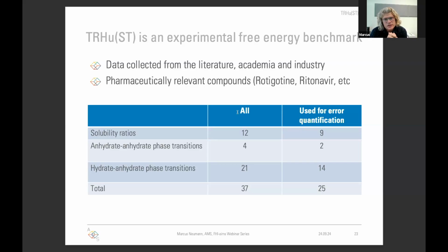Now you may wonder, why is there so little data? Well, the reason is that a lot of conditions need to be fulfilled. The crystal structures of all experimental forms must have been solved. There should not be massive disorder, because otherwise the entire problem becomes more complicated. And then the phase transition has to be characterized, so there needs to be a thermodynamic variable before and after the phase transition, and the phase transition has to be reversible. And so if you look at the literature, there are data sets, but they're hardly ever complete. Even if they are complete, they may not fulfill all quality criteria. So we in total have 37 free energy differences, but there are only 25 we really trust. So whenever we extract numbers, those numbers are only against 25. So TRHu(ST) is also an experimental free energy benchmark.